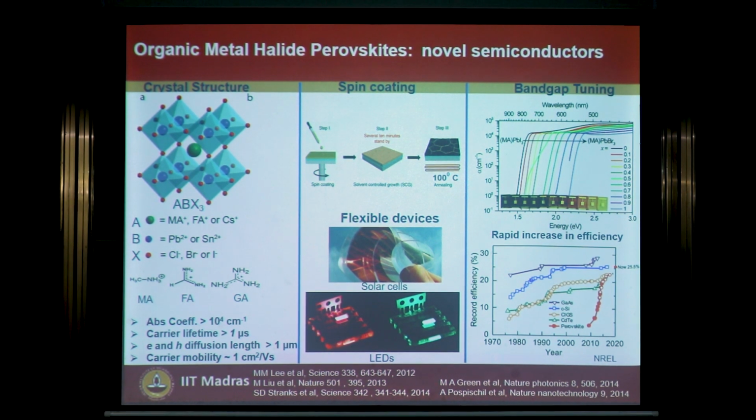I'm trying to see if there's any kind of band structure based explanation. Yes, the explanation behind the band structure is, one, that it is pretty much defect tolerant for many of them, and it's a direct band gap system, and the ultrafast cooling of charges is pretty fast. Within less than 1 picosecond, all the hopping of charges happens in the conduction band, and everything seems to be good, intact. Even though it doesn't occur in nature, it's a man-made mineral, it seems to be working well.